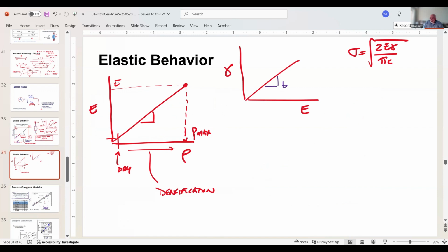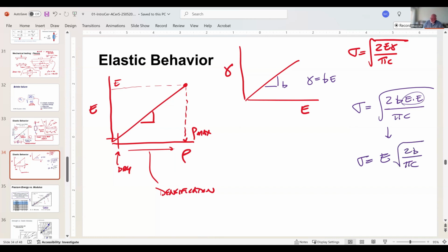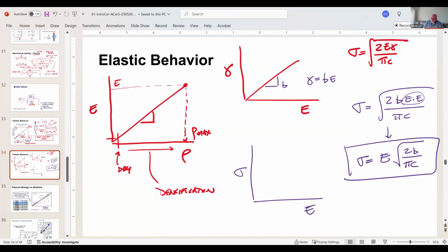So if that's the case, what I could do is come in here and say sigma is now equal to the square root of 2BE times E, because I've got gamma equal to B times E, divided by pi c. Now what happens is that strength is equal to E, because I take my E squared out, times the square root of 2B over pi c. Why do you care? Well, if I end up with a situation where strength sigma versus elastic modulus gives me a linear relationship, the slope of this line is the square root of 2B over pi c.